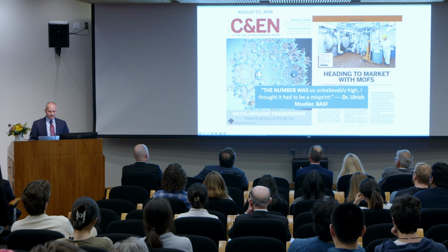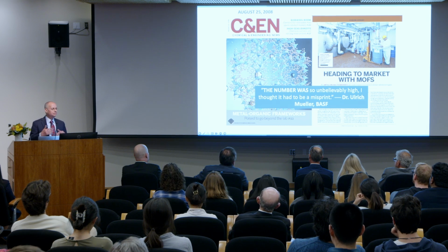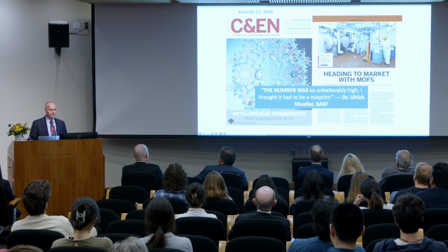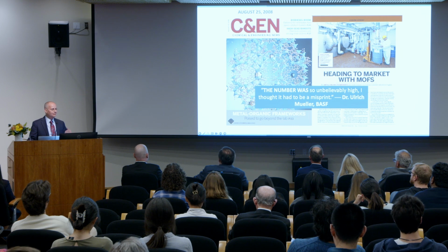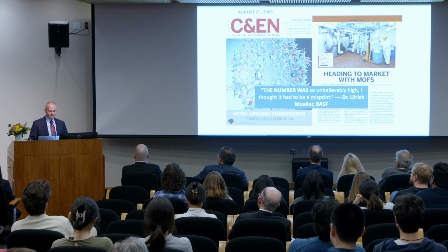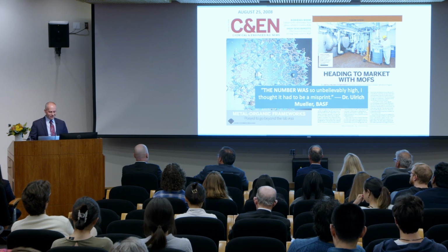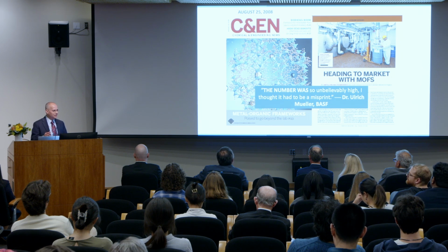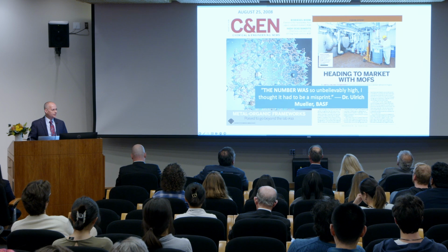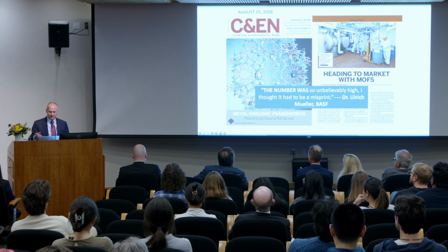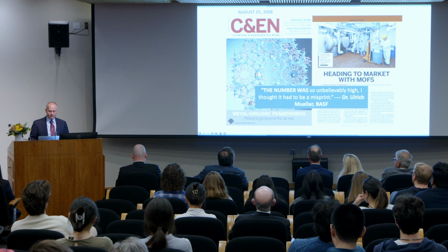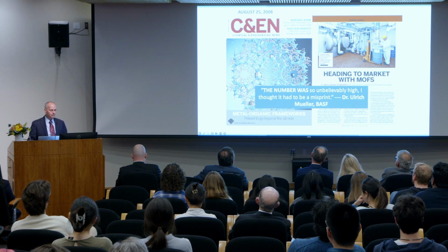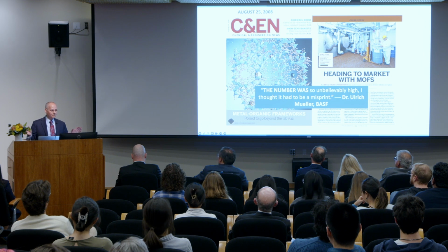So later, BASF, that was when I gave the first talk about that material in '99, I met BASF colleagues who then showed the world that in fact MOFs can be scaled up to multi-ton quantities. And you see this plant here where the MOF, which is like a powder, like a baby powder, in this case it's zinc MOF, is being filled into these large blue barrels. That was the start of a field.